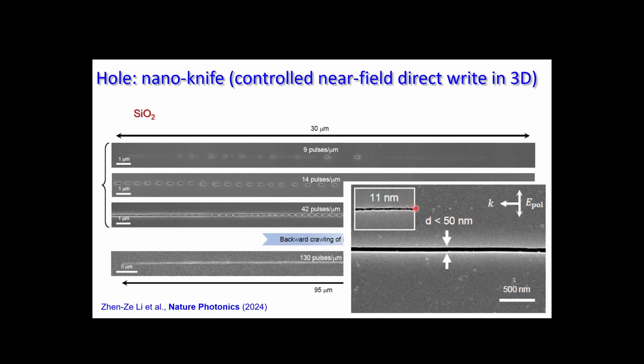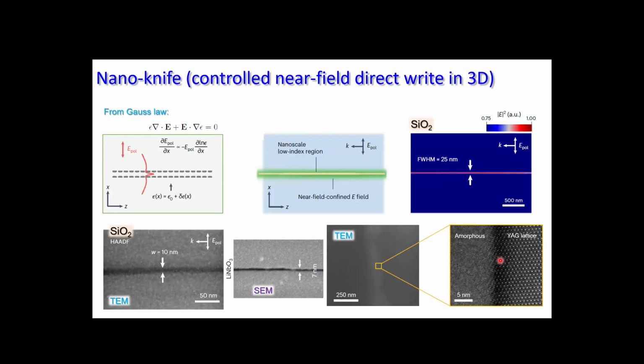And so just to see the smallest features, it was a short etching time, we recognize that the line can be very, very narrow. If you etch longer, certainly it's widening. But here the aspect ratio is enormous. You have tens of nanometers width for 100 micron length. So what is the physics here, what is defining this kind of modification, which is not spreading laterally?